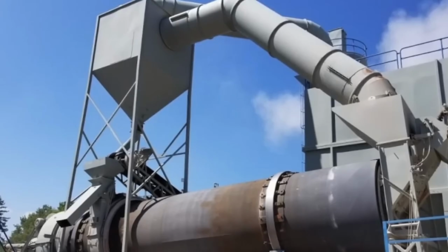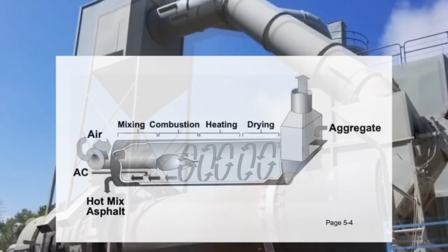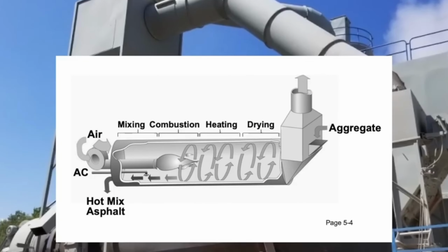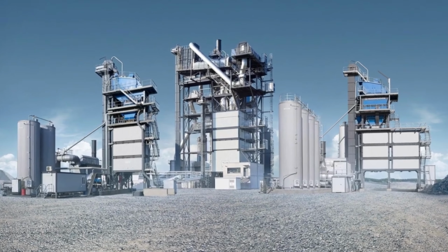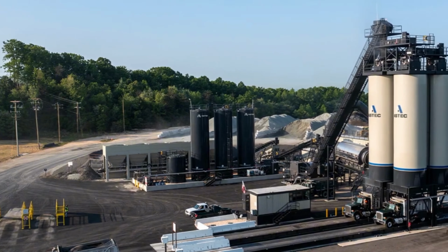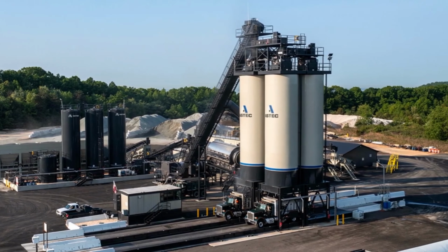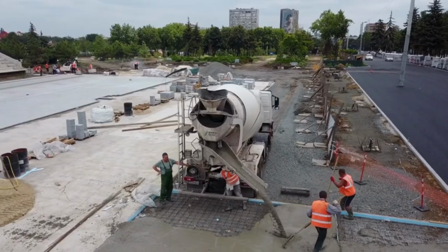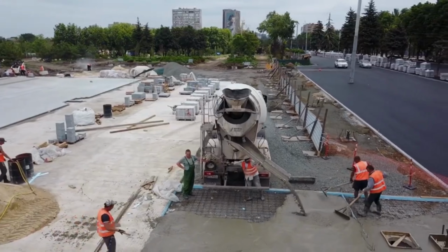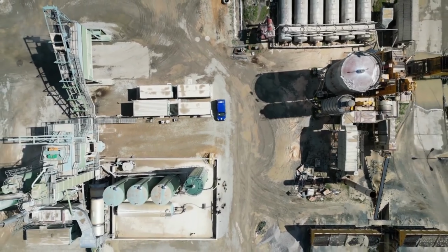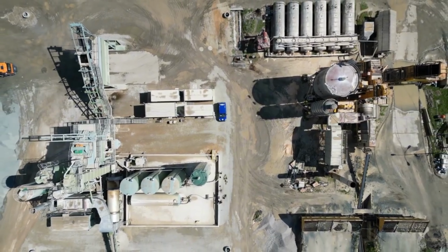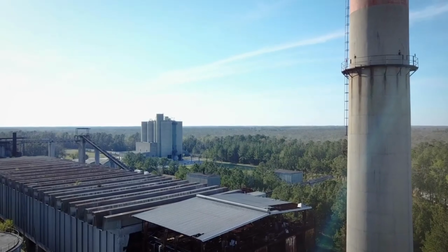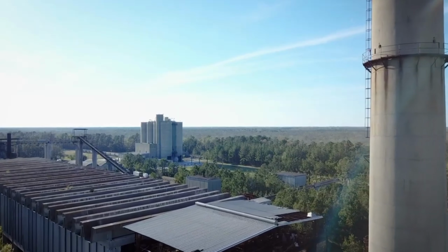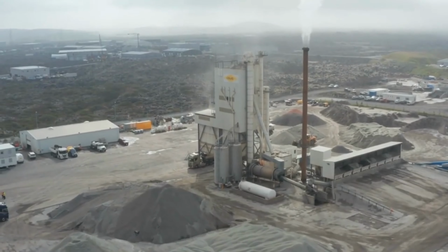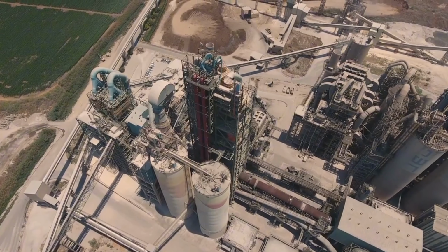At the asphalt plant, aggregates first enter the drying drum, a massive rotating cylinder heated by powerful burners. These burners, fueled by natural gas or oil, blast temperatures exceeding 300 degrees Celsius into the drum as it turns. Inside, drying flights lift and tumble the stone, exposing it to hot air and evaporating all moisture. This step is critical because any trapped water would instantly vaporize when mixed with hot asphalt binder, causing steam explosions and improper coating. Sensors monitor moisture content continuously, saving fuel by adjusting burner output.